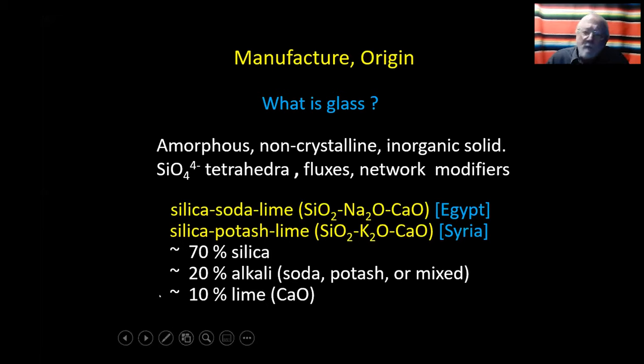Well, the problem with making glass is the major component, the silica or sand. You just can't melt it. It requires 3,100 degrees Fahrenheit or 1,700 degrees centigrade. So that's where the alkali comes in. The alkali acts as a flux and allows the silica to melt at a much lower temperature, around that of making ceramics.